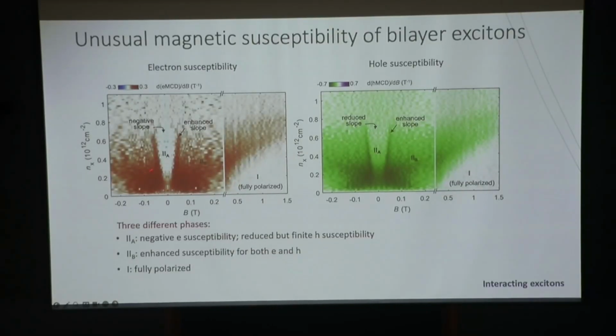In the 2A phase, you can see the colors blue and red have opposite signs. So basically, the effective susceptibility changes sign for the electrons, but it's reduced for holes. In the 2B phase, you have large susceptibility. And in the 1 phase, they are fully polarized, and you don't have any polarizability anymore. The other thing to notice is that this 2A phase expands with exciton density until the Mott transition where the exciton is gone. So this is really an exciton-exciton interaction-driven phase.